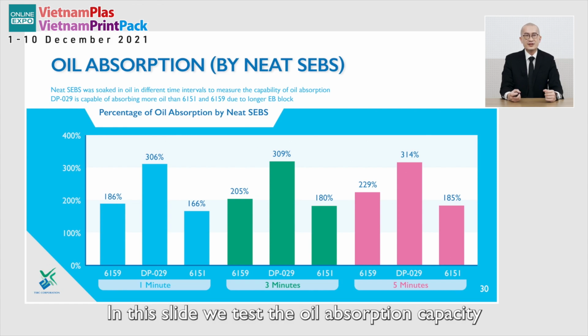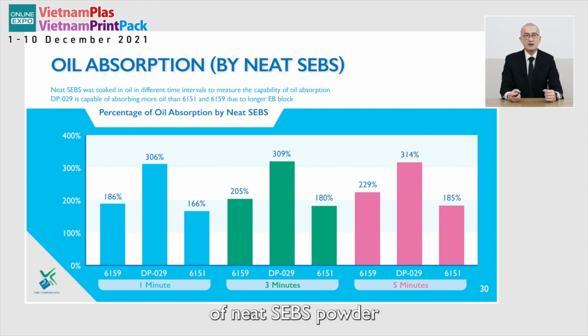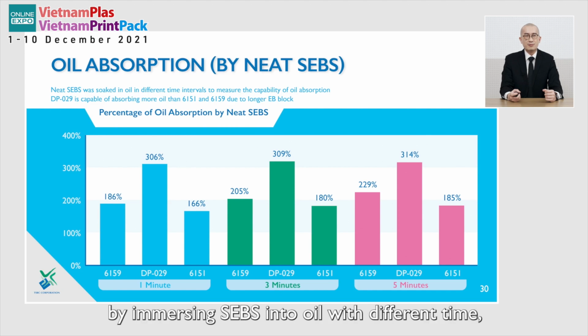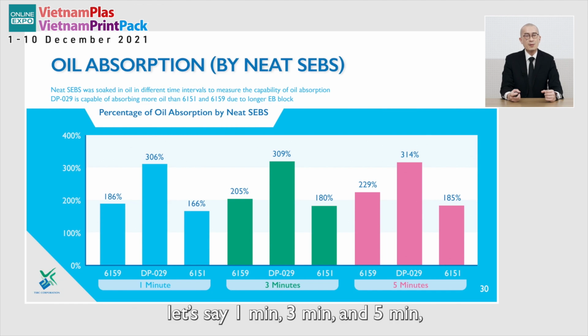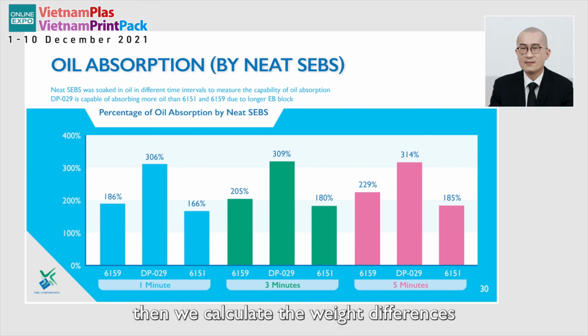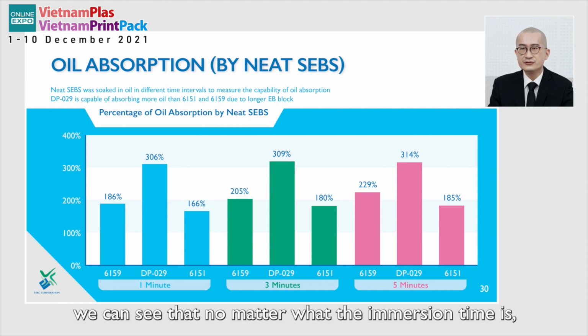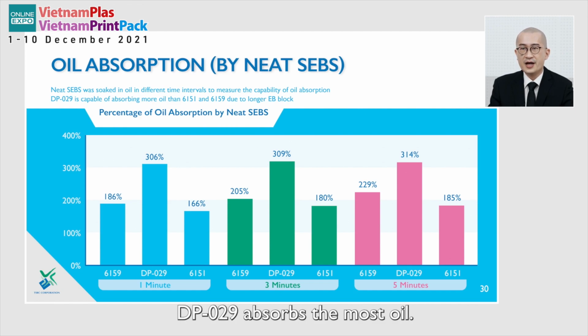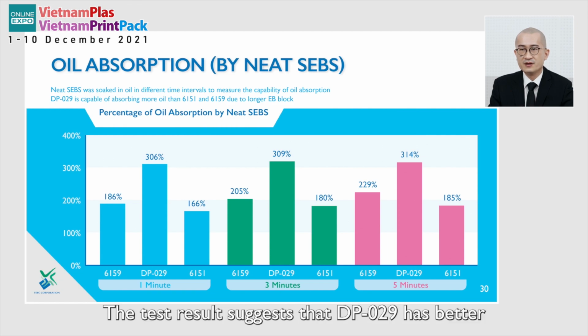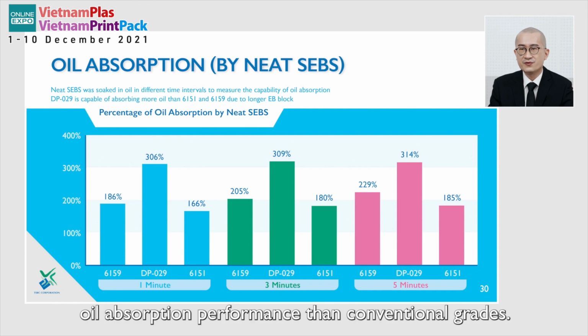In this slide, we test the oil absorption capacity of neat SEBS powder by immersing SEBS into oil with different time. Let's say 1 minute, 3 minutes, and 5 minutes. Then we calculate the weight differences before and after immersion. From the test result, we can see that no matter what the immersion time is, DP029 absorbs the most oil. The test results suggest that DP029 has better oil absorption performance than the conventional grade.